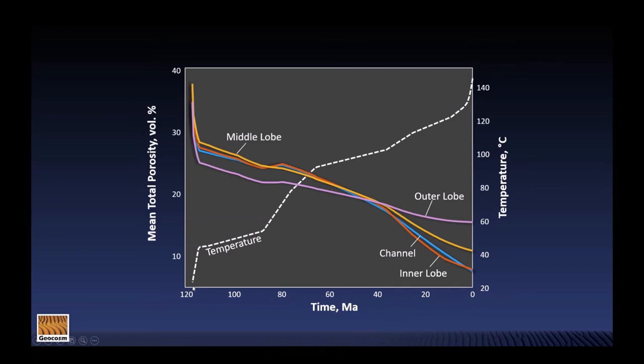And so what we see is that shortly after burial, we had a very rapid pulse of burial. That had a correspondingly rapid increase in effective stress. And so shortly after burial, we had a very rapid porosity loss that was driven by mechanical compaction. Now, interestingly, at this point in the burial history, we're actually predicting lower total porosities in the outer lobe here compared to the channel. And the reason for this is that we have a bit more of those ductile shale rock fragments mixed in here, and we also have some detrital clay. And that detrital clay, although it is microporous, is partly filling in intergranular pores. So the solid part of those clay particles, in fact, is reducing the porosity compared to what it would otherwise be if we didn't have that detrital clay in the system.